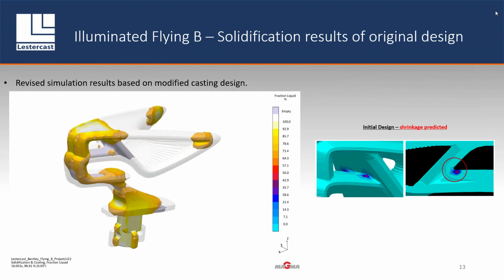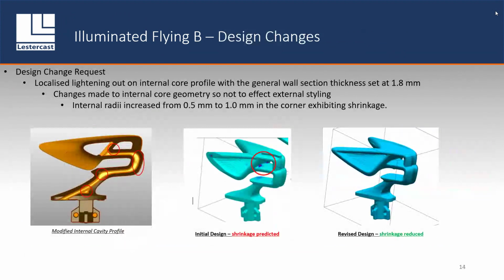This is a view of the solidification. You can see here there's two isolated sections down in the corners here around the core, which was manifesting itself as porosity, or shrinkage rather, in the casting. So quite a lot of to-ing and fro-ing and design changes later, we managed to change the profile, which was this internal shape here. So we did have a little bit of scope to change that. Obviously, it was an internal shape, so Bentley themselves weren't too worried about that. They're a bit more flexible. And we were able to increase the corner radii here from 0.5 millimeter to 1 millimeter, which sounds absolutely nothing, but we're talking about small margins here.